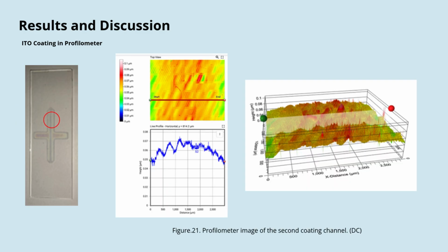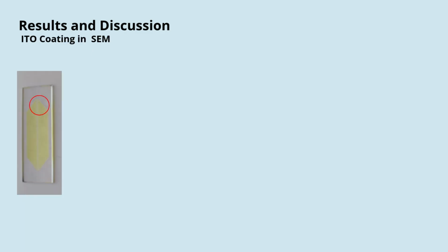In the optical profilometer, the results of the second coating did not come out as desired. It is thought that this is due to the transparency of the second coating. The thickness cannot be easily made out from the profilometer as the reading was faulty.